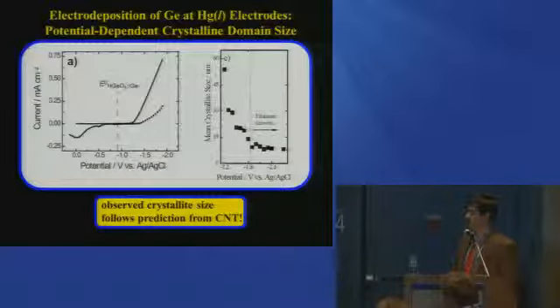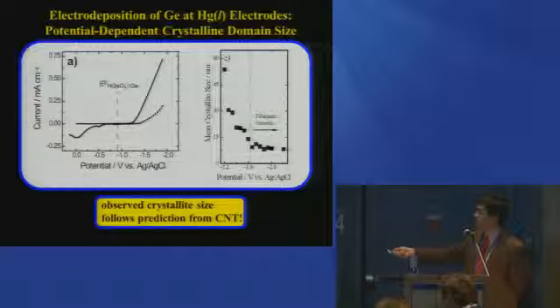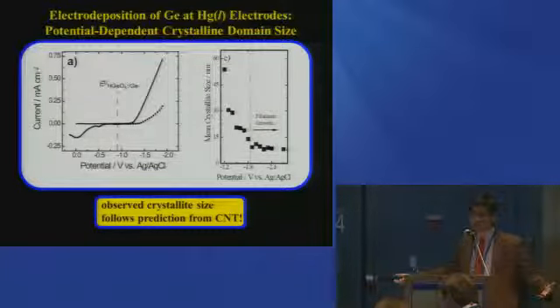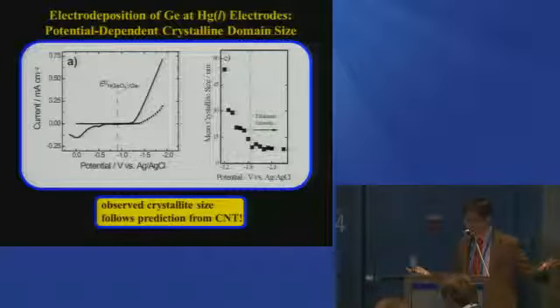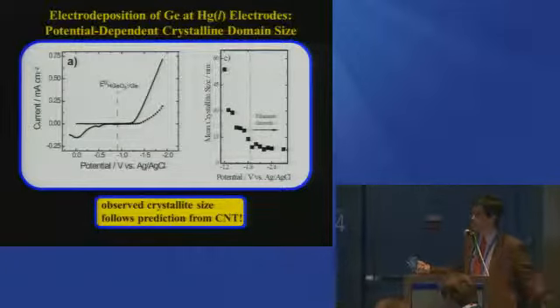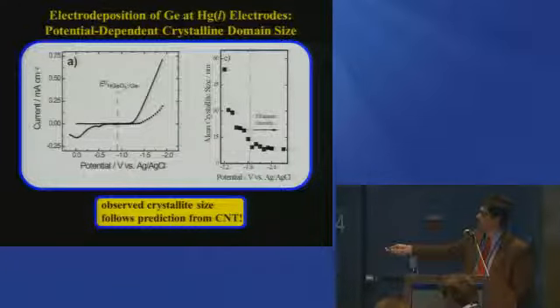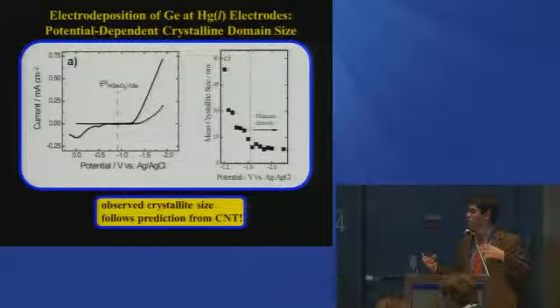If you start going with a fine-toothed comb, looking at those crystals, you'll find that the crystals are actually a function of the potential that you're doing your electrodeposition at, which is actually a little bit not obvious. It certainly wasn't obvious to us. And what we really noticed is that these crystallite sizes changed the further and further negative we went, or under conditions where we really were driving germanium into the mercury electrode.